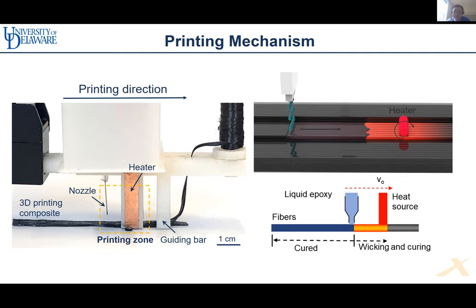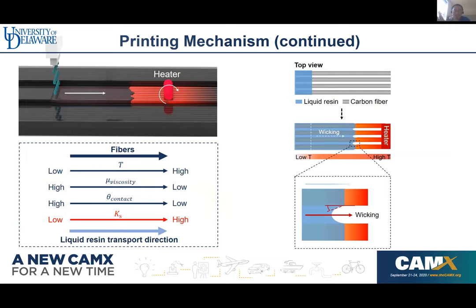Here is our schematic and also the 3D printer head design. And here is the printing principle, the design principle. Once we apply the heater, we can control the temperature, which actually depends on the thermal property of our liquid resins. So you can see we can create a gradient distribution along the fibers from the low to the high temperature, right?